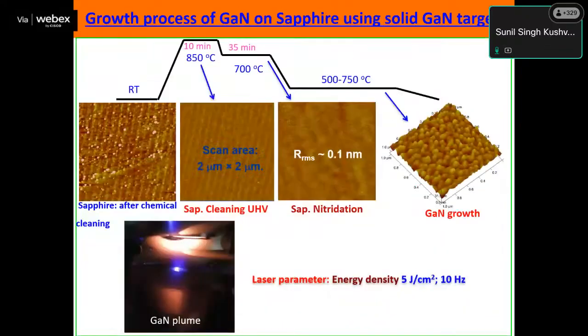Here I wanted to show how important cleanness is in the whole process. This is the sapphire substrate we cleaned chemically before loading in the load lock chamber. We can clearly see some small dust particles are still there. After that, we put it inside the UHV system, from the load lock chamber to the buffer chamber. We heated it up to 850 degrees Celsius. Then we took it out and did the AFM. You can clearly see we are not able to see any dust particles, so it means the surface is already very clean.